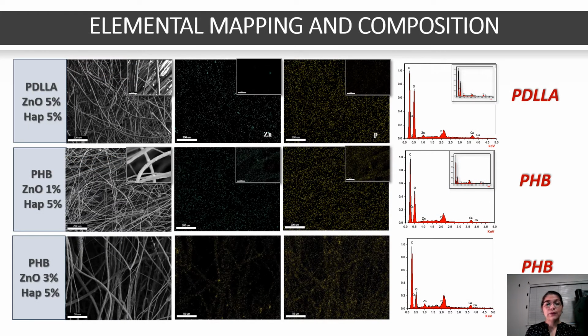Through elemental mapping of zinc and phosphorus, the presence of both nanoparticles in the samples is identified, observing more agglomeration points for zinc oxide. This is due to the tendency of these nanoparticles to form agglomerates from a certain concentration. It is good to take into account that these nanoparticles are 2 times smaller than the hydroxyapatite nanoparticles. Apparently, the polymer matrix presented a higher affinity for hydroxyapatite, which is why a better dispersion of these nanoparticles was observed throughout the fibers.